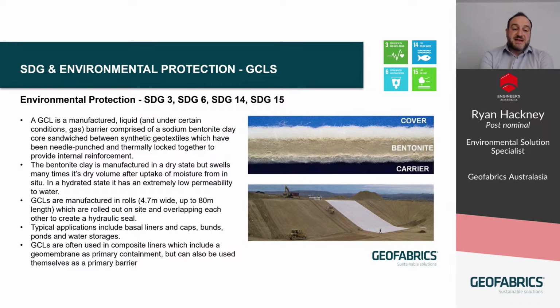Here in Australia, GCLs are manufactured in rolls that are 4.7 meters wide, and they can be manufactured in any desired length, but typically up to 80 meters. They are rolled out on site and overlapped like you saw in those previous photographs. That overlap section is 300 millimeters wide, and that creates a hydraulic seal. Typical applications for GCLs include basal liners, caps, ponds, and water storages. GCLs are often used in composite liners, which also include a geomembrane as primary containment, but in fact, GCLs can also be used themselves as a primary barrier, depending on the chemistry and the site-specific situation.